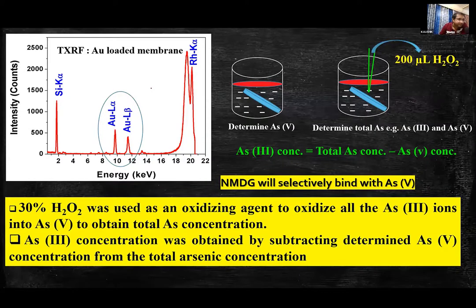So this is the TXRF spectra of a gold loaded membrane. You can clearly see the gold L alpha and gold L beta peak. Now, as we know that this NMDG membrane very selectively binds arsenic 5 species, but we have to determine both arsenic 3 as well as arsenic 5. So that's why I have developed one strategy.